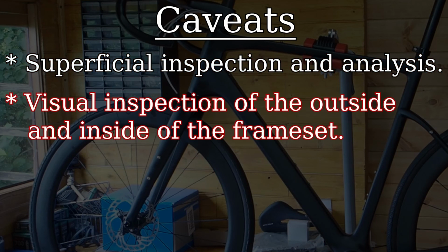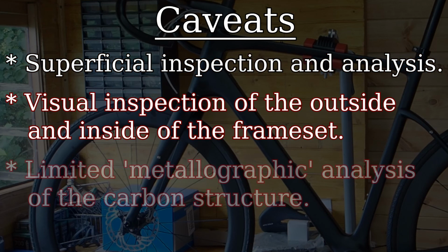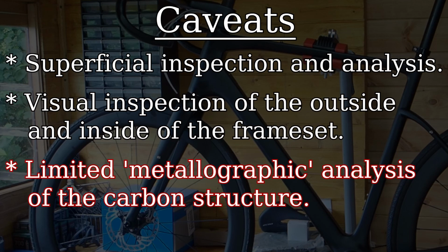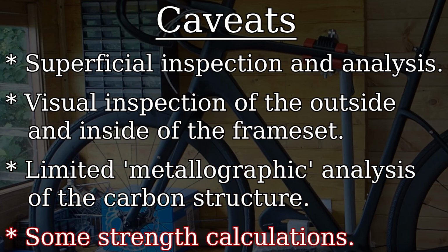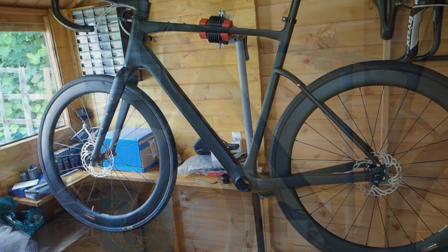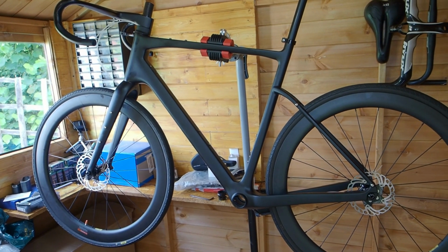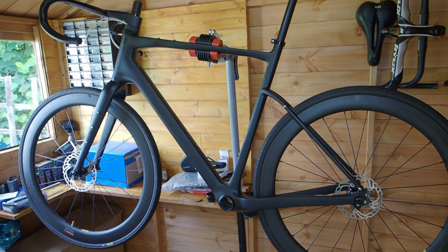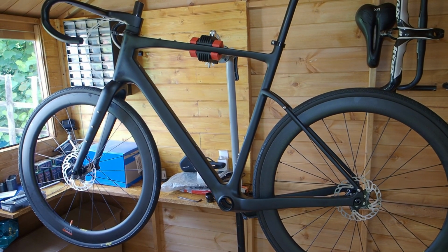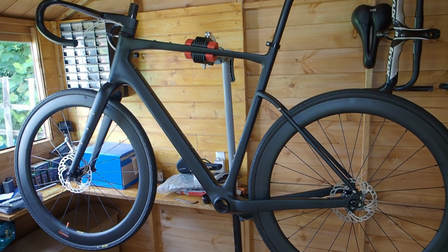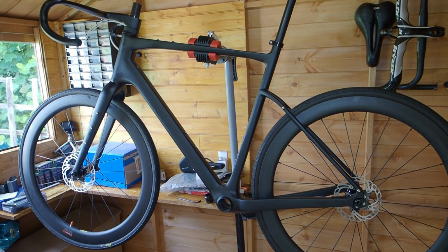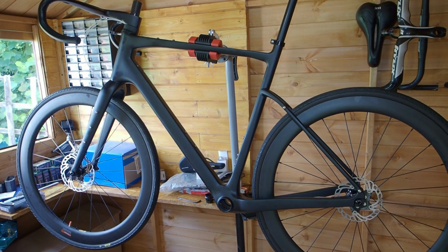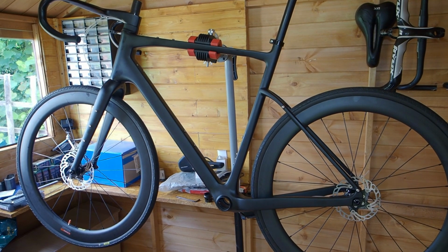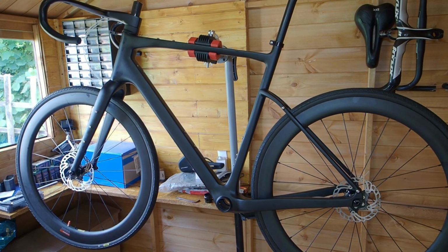It was limited to visual inspection of the frame set parts, some analysis of the carbon structure, and I've also carried out some strength calculations. I suppose the bottom line here was I was looking for any indications that the frame may not be safe. Overall, no alarm bells rang for me. Indeed, I was quite pleased and surprised about the quality of the carbon layup, particularly given it's a budget frame. I didn't find anything that would suggest the frame is of substandard quality or would be unsafe. My only real area of concern is that seat post, but that's relatively cheap and easy to replace.